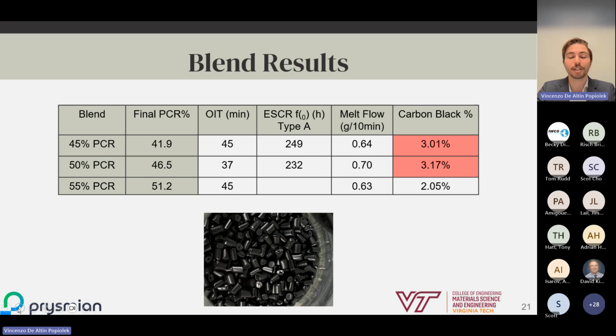For carbon black percentage, this is the one category where we did face some issues. We slightly overshot the top end range of 3%, which is allowable. We, however, believe that this is more a reflection of our inexperience with the compounding and blending process than it is reflective of the blend that we chose. We aimed to compound in at 2.75%, however, slightly overshot this. We do not believe this is something that the Prysmian group would have issues with on their lines.